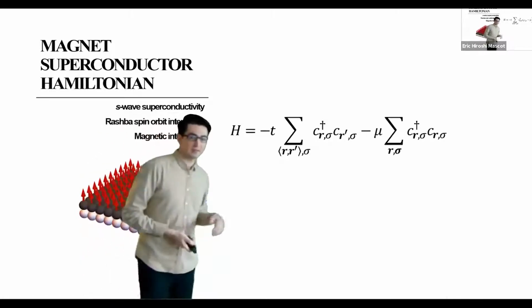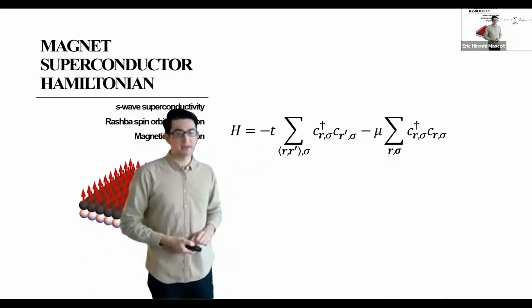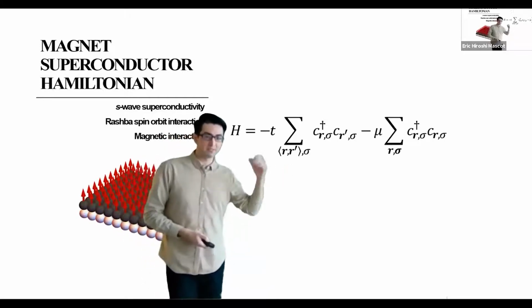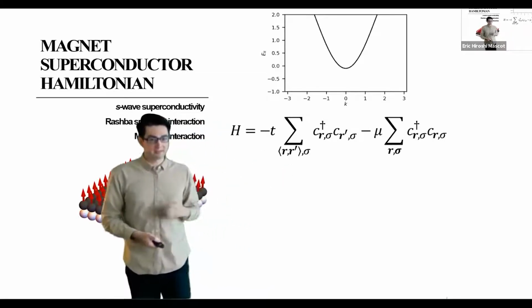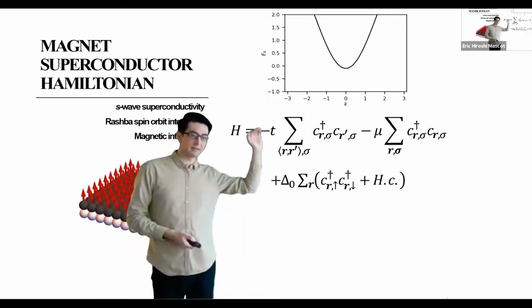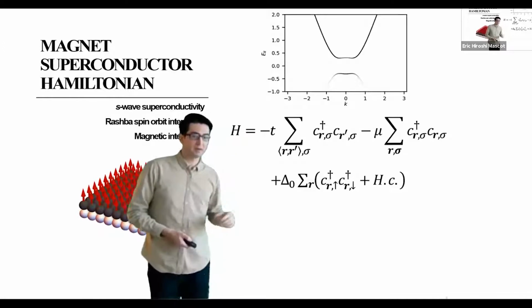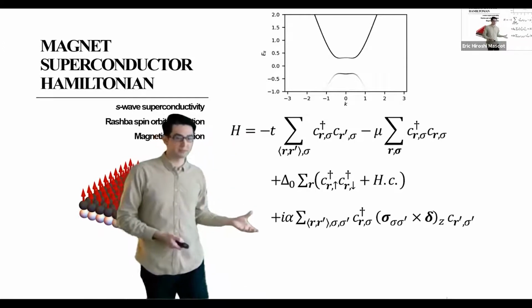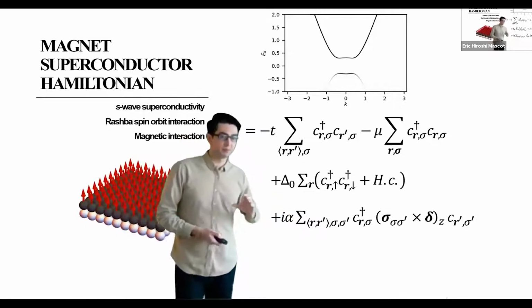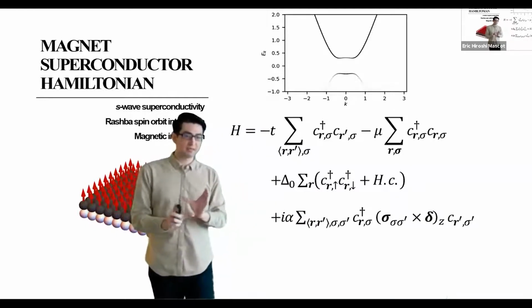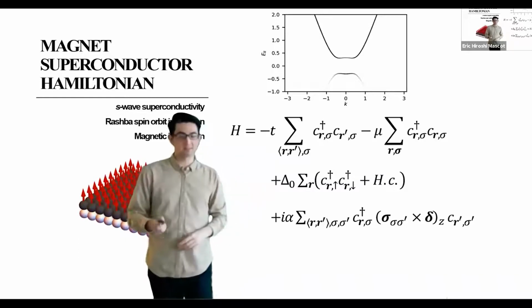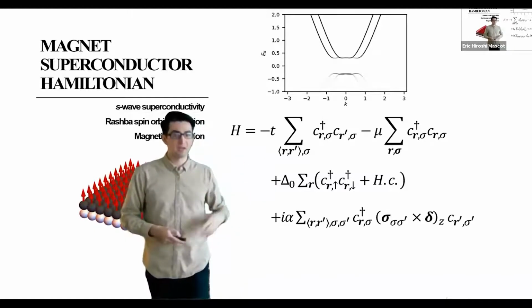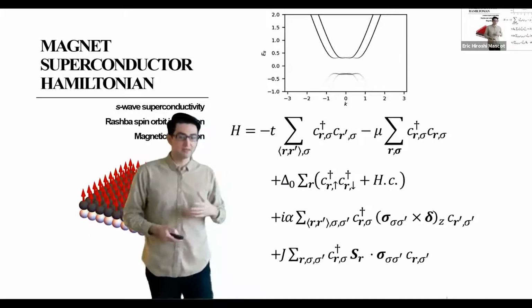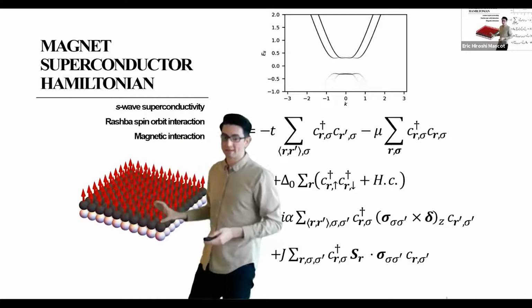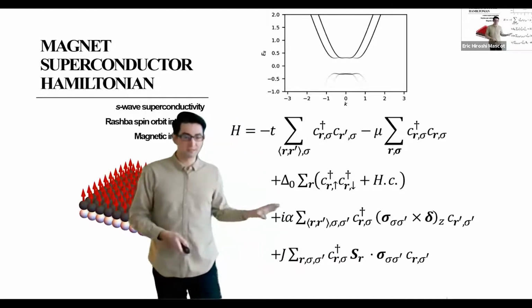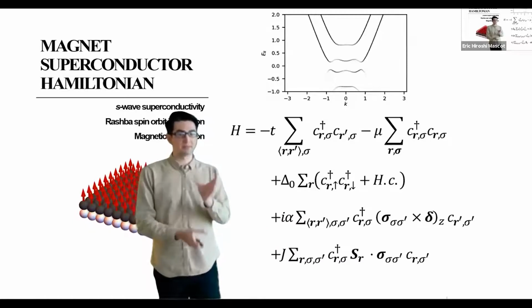So the first term of the Hamiltonian is this simple tight binding model, which gives us a band. And then we add superconductivity, which will gap the band at the Fermi energy. Then we add a Rashba spin-orbit interaction, which couples the spin to the momentum. And so what happens to the dispersion is that we lift the spin degeneracy by splitting the bands sideways, like so. And then lastly, for the magnetic interaction, these magnetic atoms act as a local magnetic field, like a Zeeman term, which splits the bands up and down, like so.